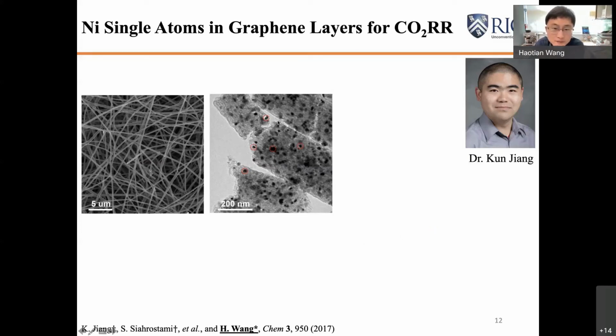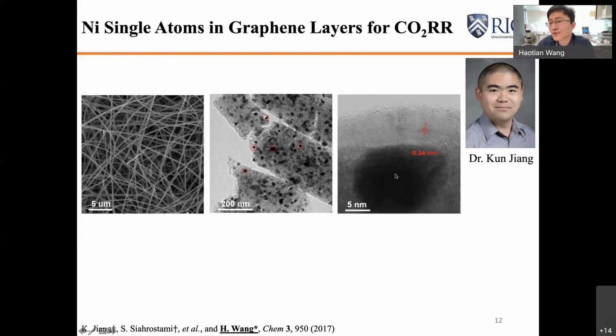As you can see, we have these carbon nanofibers formed, embedded in which we have a lot of black dots. And if you zoom into those black dots, those are actually nickel nanoparticles. But there is a very unique core-shell structure here. As you can see, the nickel nanoparticle is tightly surrounded by a few layers of graphene. And that actually provides us a great opportunity, because those nickel nanoparticles are not the wanted ones, since we don't want nickel nanoparticles to generate hydrogen, right? But the good thing is those graphene shells tightly surround the nickel nanoparticle to block the direct contact between the particle and water, so the hydrogen evolution can be blocked.